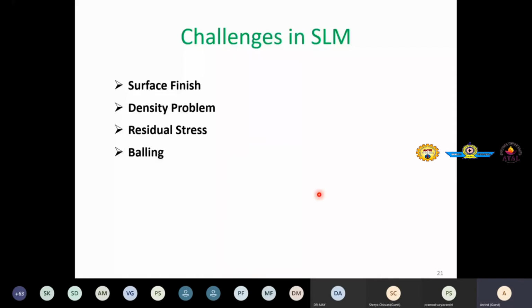And if you want to achieve better surface finish after printing, then we have to adopt some post finishing operation. But those post finishing operations can finish the exterior surface, but interior surface finish is again a challenge. Okay, then next challenge is density problem. We typically want the part density to be close to true material density, something like 99.9%. But because of many reasons, like bad selection of process parameters, some defects like porosity, the density is falling behind that 99.9%. And this will lead to issues like a lot of porosity formation in the layer, then integrity of the two layers, whether they are adjacent or consecutive layers. So that will create interlayer issues and all.